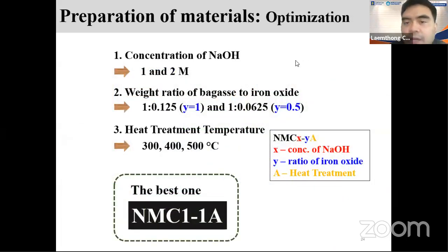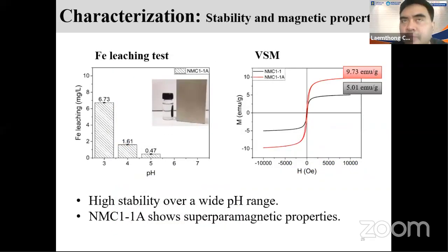We actually did a little bit of optimization with this. We studied a little bit when we tried to publish this paper, and the reviewer said, oh, the optimization seemed to be quite okay, so they let us publish this work. We also tested the leaching test, and we found that at very acidic conditions, this is not good to use.